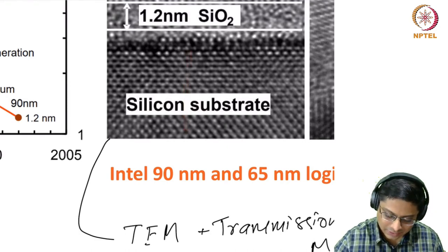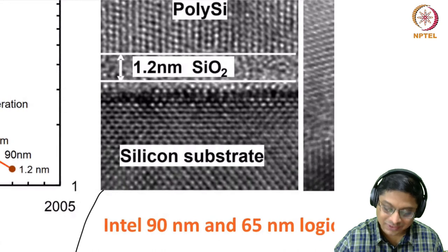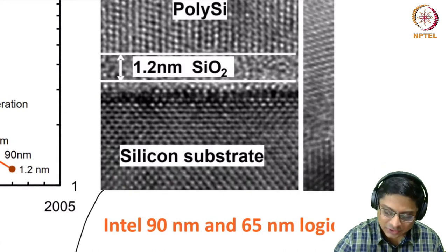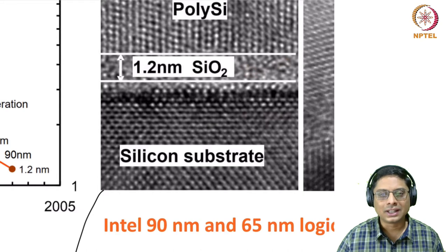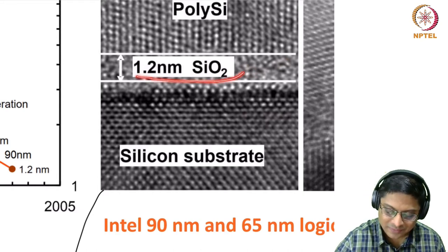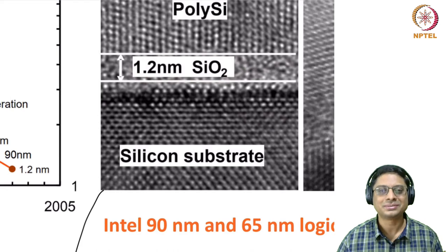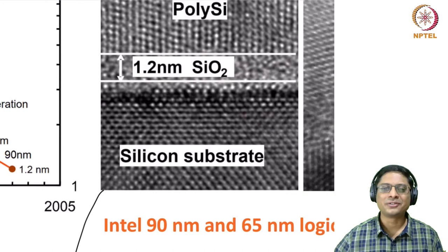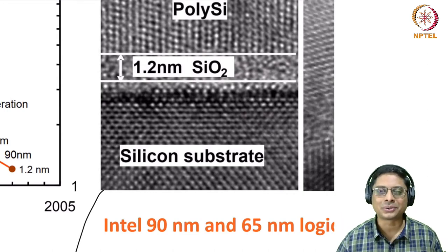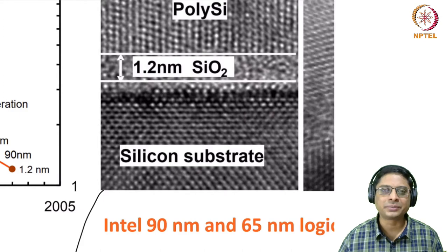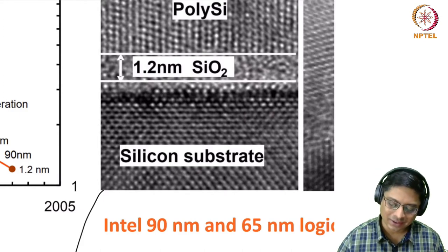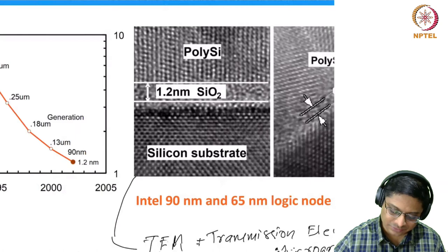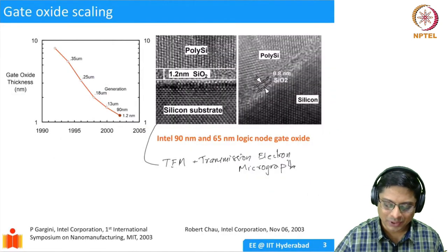On top of it, you see the oxide, which is an amorphous material. So you don't see that orientation, you don't see this perfect lattice arrangement of silicon. You see some random silicon and oxygen atoms. And the thickness is just 1.2 nanometers. You might wonder how we took this image. It requires an equipment called a TEM, which costs maybe up to $10 million or so. It's a very, very expensive equipment. With that, you can take this image. So you have the silicon substrate and 1.2 nanometer oxide.